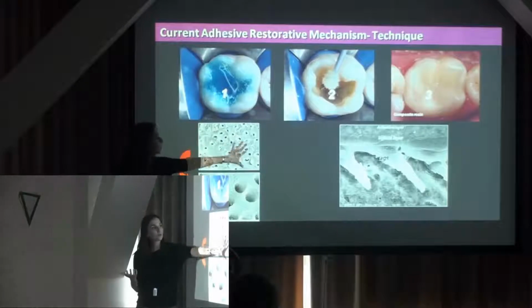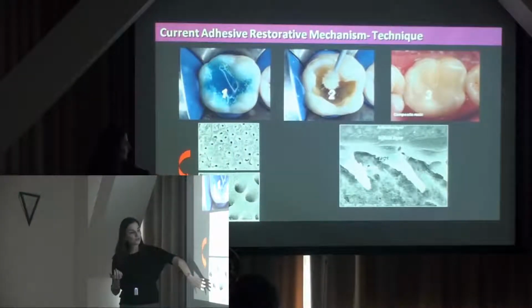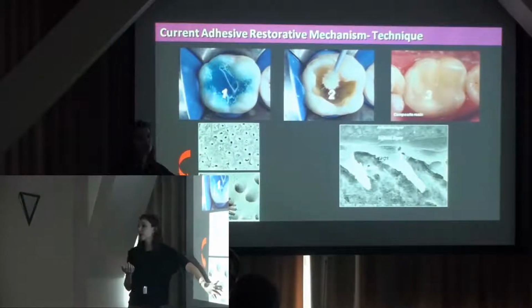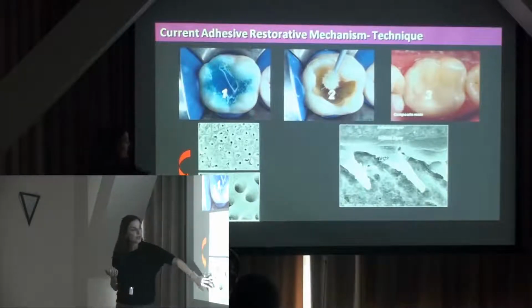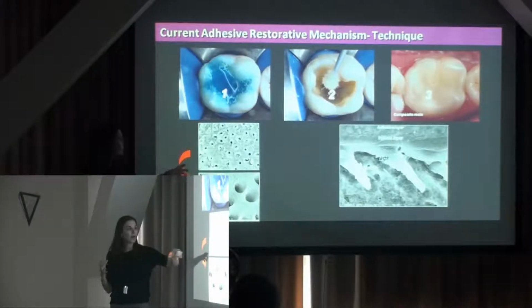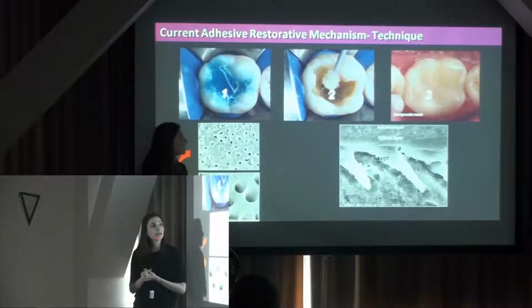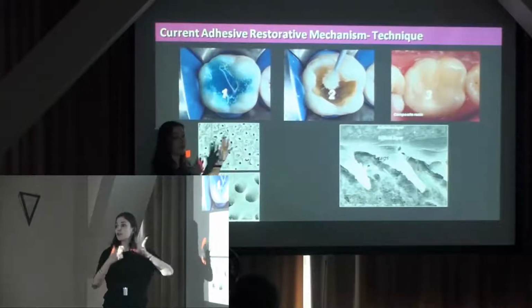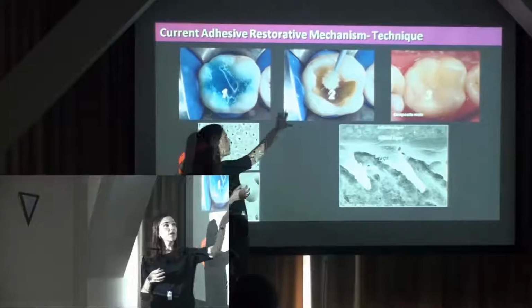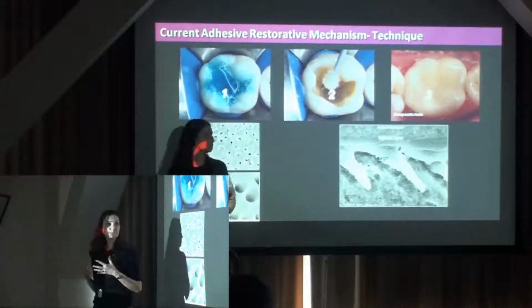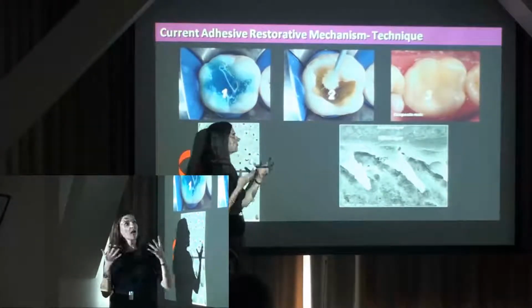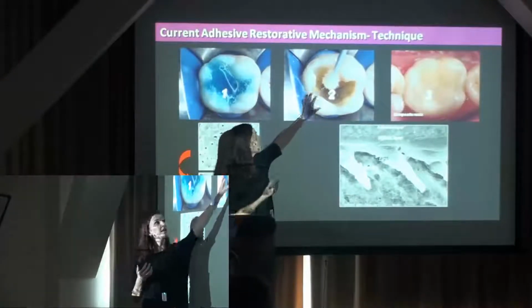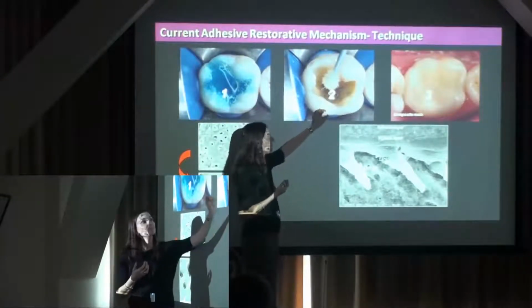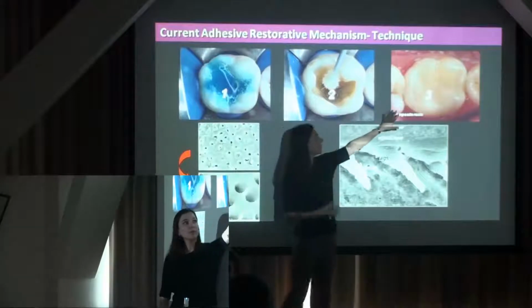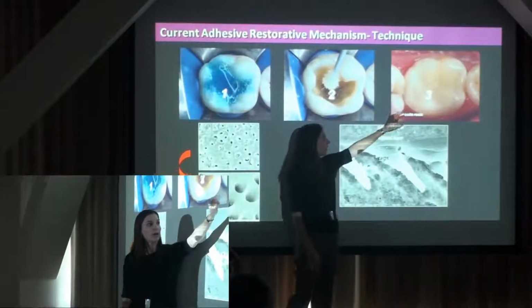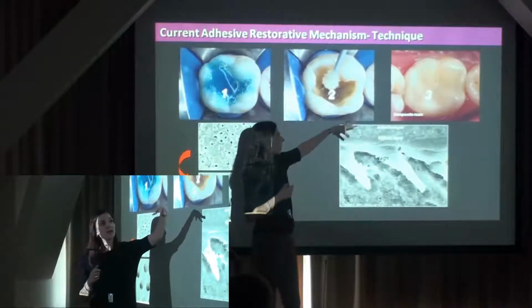So once we superficially decalcify the surface of the tooth, we have this very rich collagen-based layer. These dentinal tubules become a lot wider because we get rid of the mineral surrounding them. And then it's ready for us to start our adhesive steps. So what we use is resin, hydrophobic and hydrophilic monomers that we paint over the tooth surface. After we polymerize, we build it up with a tooth-colored material called composites, resin composites.